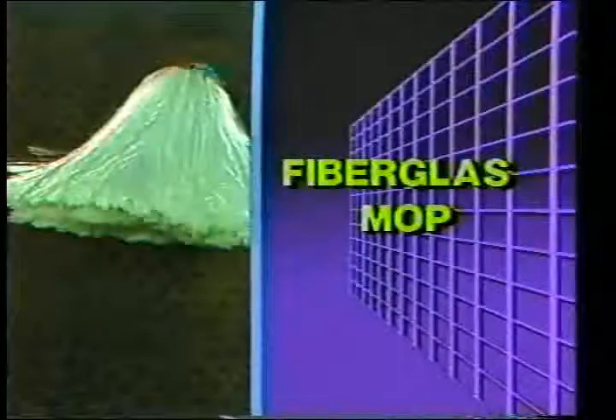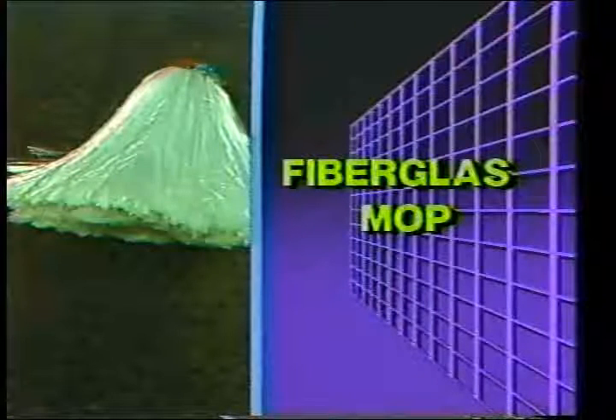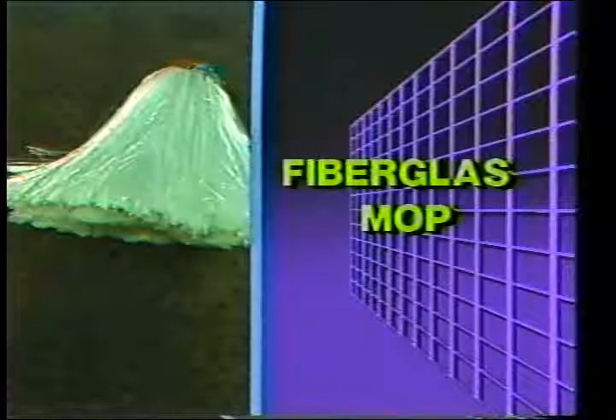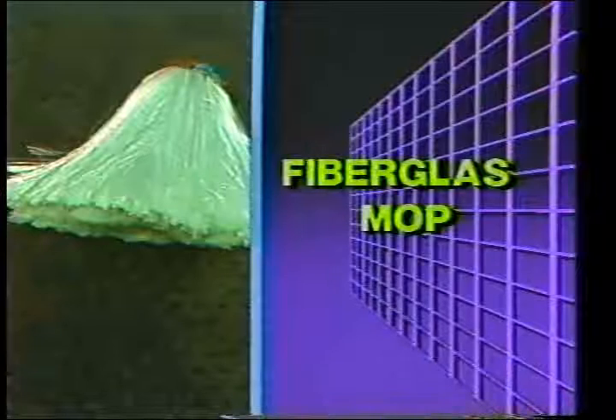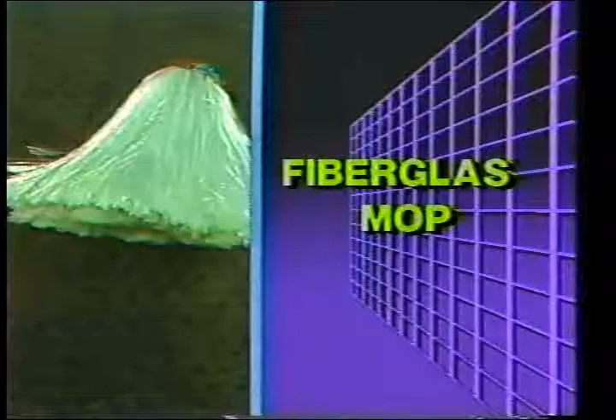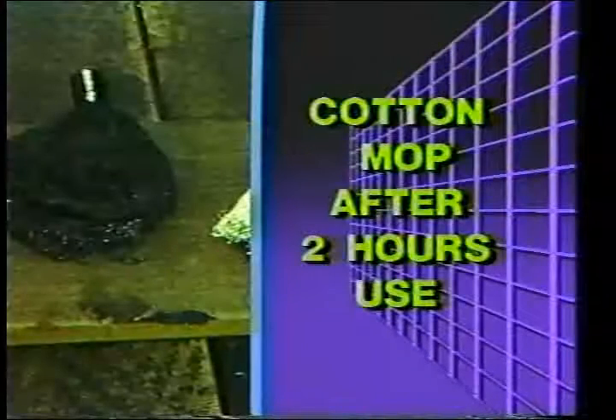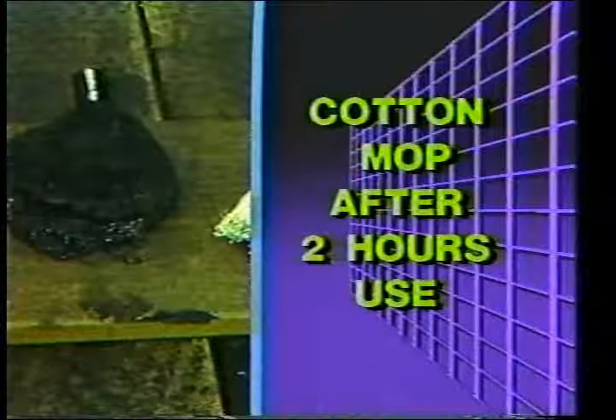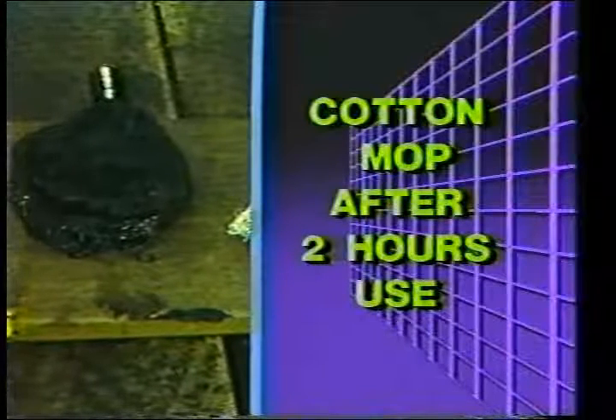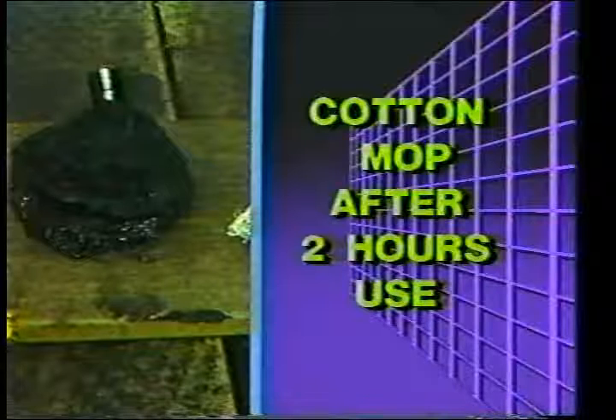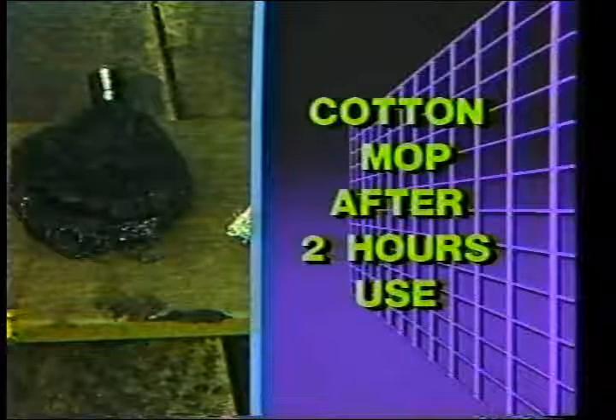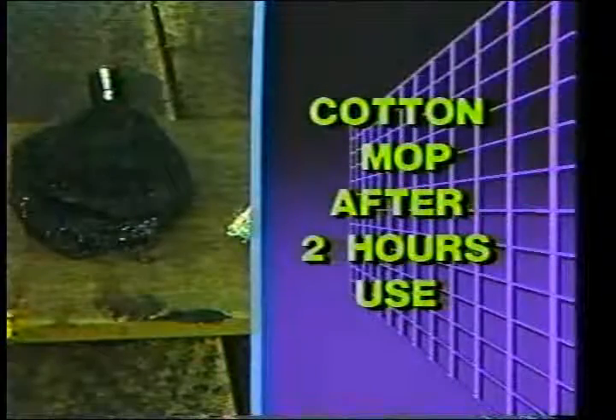Fiberglass mops are the choice of cost-conscious roofers. Fiberglass will withstand the high temperature of asphalt for days, while cotton mops char and burn in a matter of hours. Because they burn quickly, cotton mops are replaced at a rate of 2 to 5 per day per crew. One fiberglass mop, however, can be used for at least 1 week. That means a potential cost savings of $50 per week per crew.